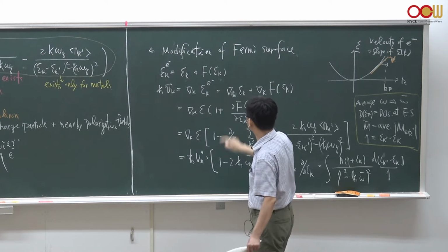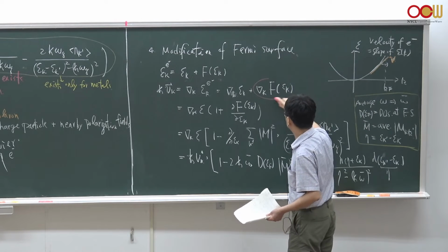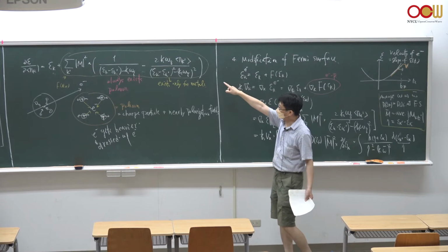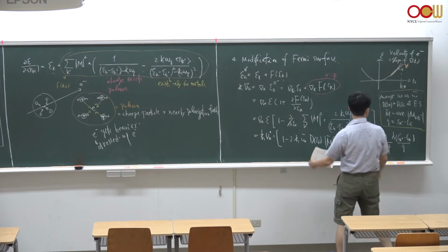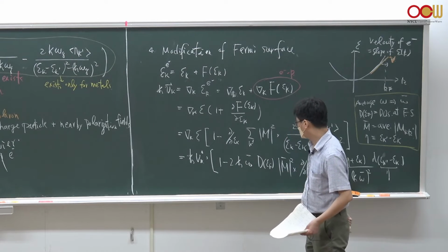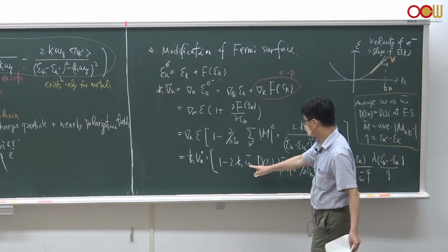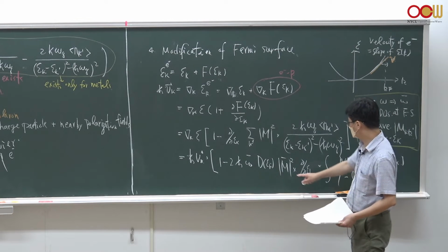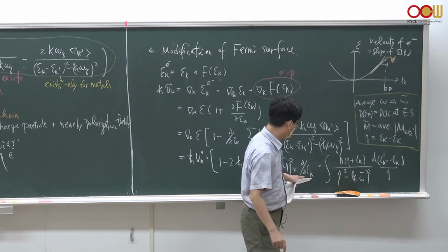One is the free electron part, which we know very well, and the second term is a new contribution from electron-phonon coupling. If you evaluate the derivative of this complicated f function, you will see that this contribution, estimated close to the Fermi surface, is minus 2 h bar times the average frequency of phonons, which we call omega bar, times the density of states of electrons at the Fermi surface, and the average matrix element squared, times the derivative of this integral with respect to epsilon k.